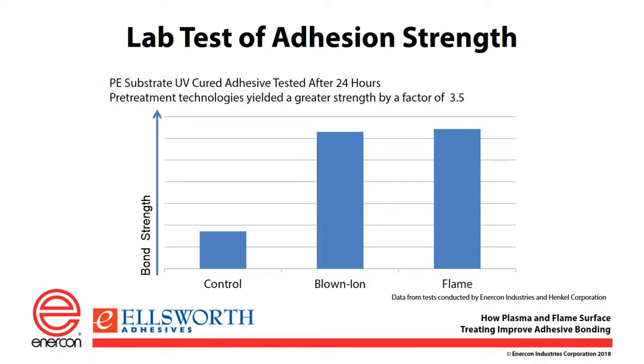This is showing a PE cured with a UV cured adhesive, tested after 24 hours, and you can see the control there, and then we treated with blown-ion and flame, and we were able to increase the bond strength by a little over three times.